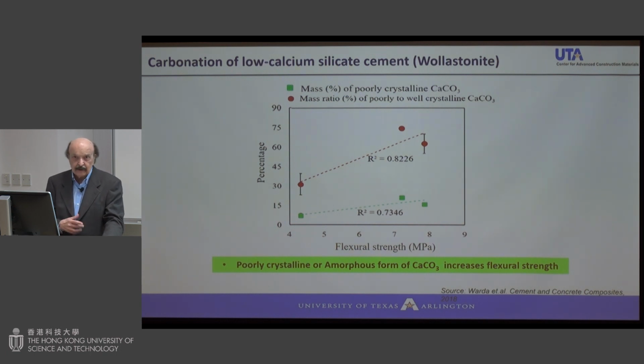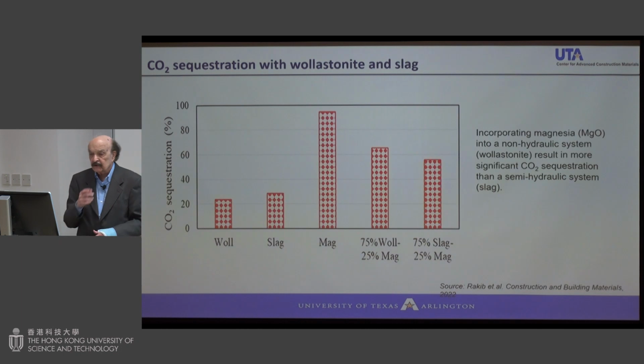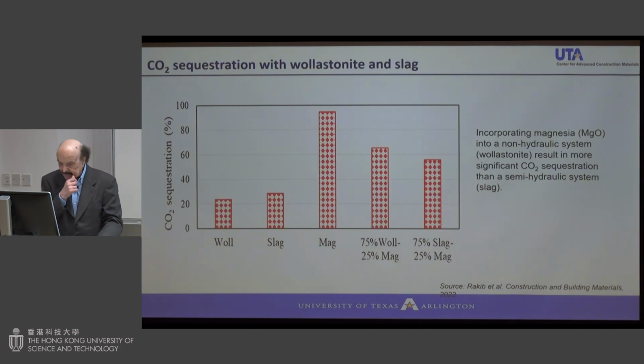And there are other ways you can manipulate the polymorph of calcium carbonate. Another way is, for example, here adding slag. So here you have how much CO2 you can sequester with wollastonite, which I already showed you. And that's slag alone, because slag has a high amount of calcium. Many people are now working on MgO or magnesia. I don't know why out here. But when you combine wollastonite with magnesia, then incorporating MgO in this non-hydraulic system can also increase carbon sequestration. So these are some of the ideas.